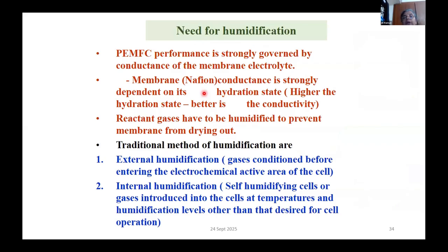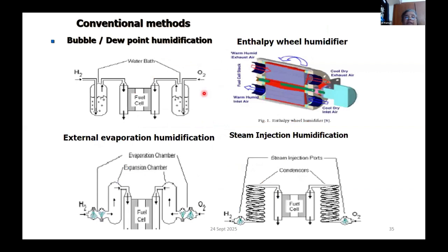So, like I said, in PEM, one of the main components is that the membrane always has to be humidified. Otherwise, the conductivity of the membrane decreases, and the performance will decrease. So the gases have to be humidified for that. There are different methods of humidification. You can do an external humidification, where the gases are preconditioned before sending them into the cell, or you can do an internal humidification where you modify your electrode structure in such a way that the water produced is retained within the cell and is useful for maintaining the humidity of the membrane. So these are the various conventional methods.